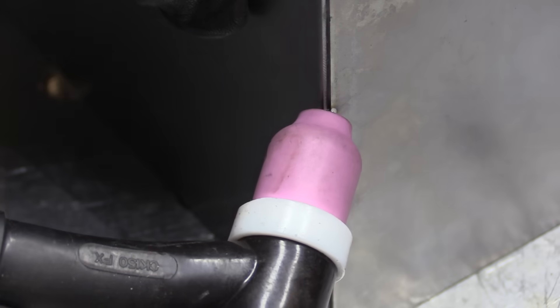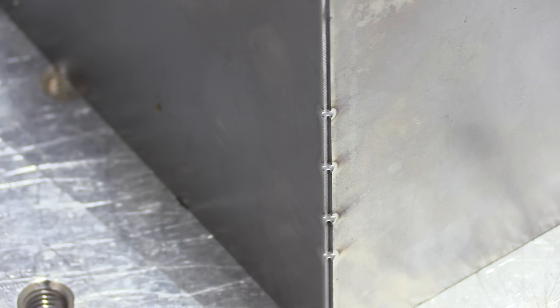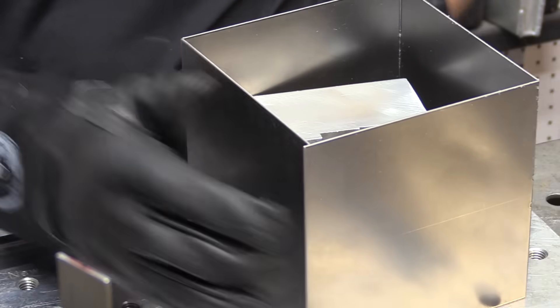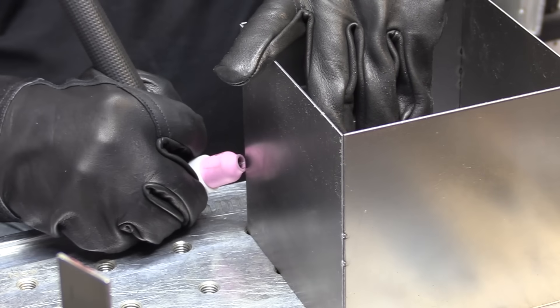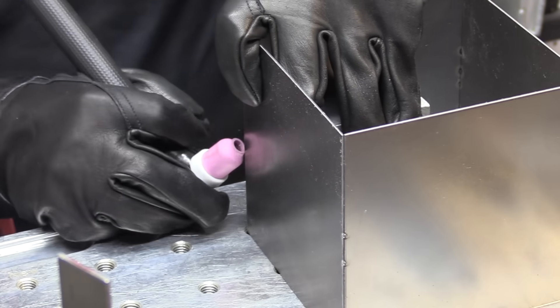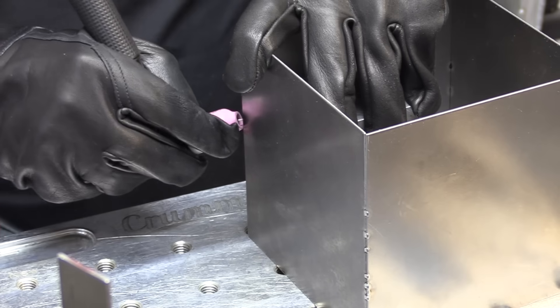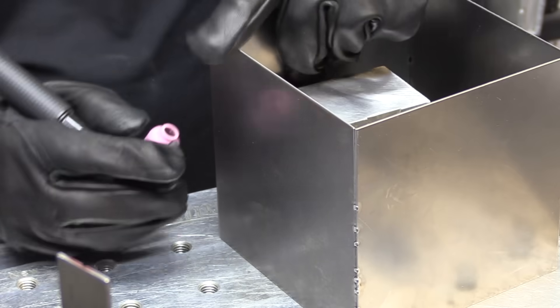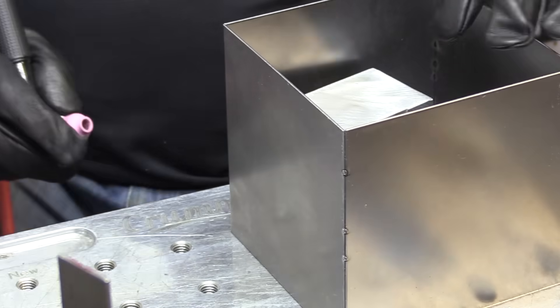Now because you're using such high amperage, it does pay to practice on some scrap metal before you do this on anything important and you can't have a gap at all. You've got to pay close attention to corner to corner fit up with no gap and a really tight arc length, and you got to get on and get off. You can't hold the foot pedal down more than maybe a tenth of a second or so.